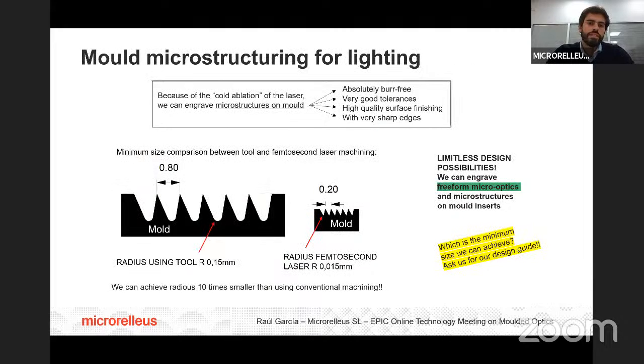Because of this cold ablation of the laser that we spoke of before, we can engrave microstructures absolutely burr-free with very good tolerances, high quality surface finishing, and very sharp edges. If we compare with the minimum size we can achieve using conventional technologies like a milling machine, we can achieve radii less than 10 times smaller than those technologies. And because we are working from a CAD file, there are limitless design possibilities.